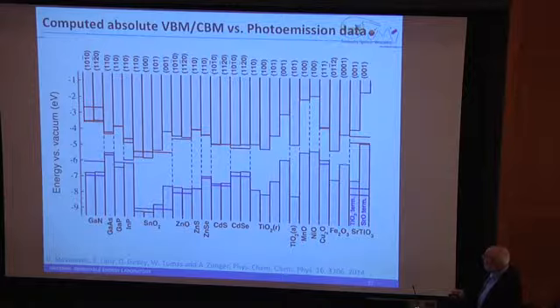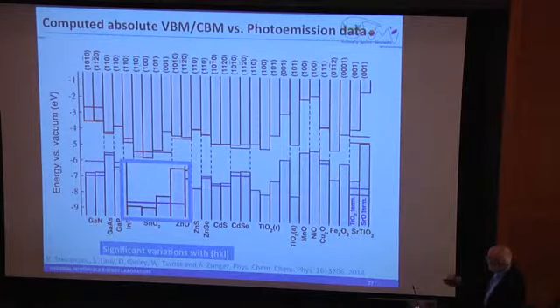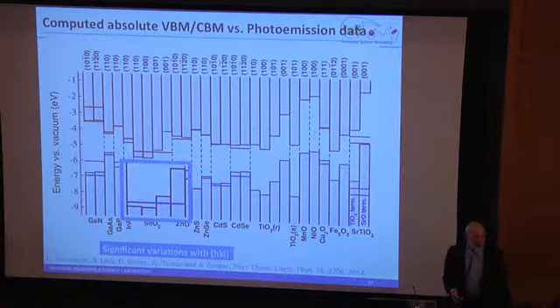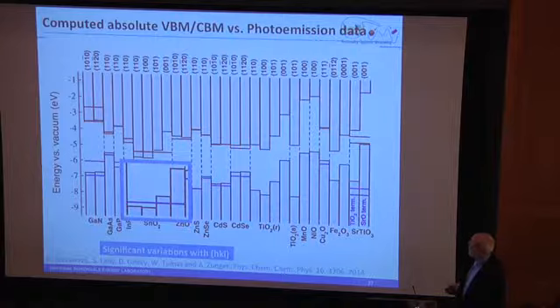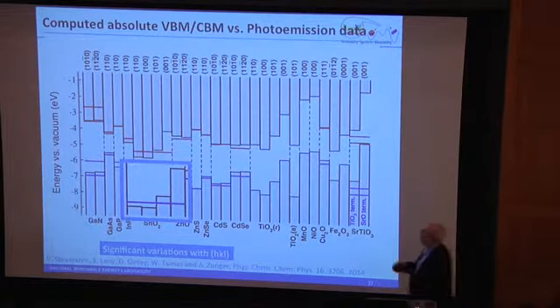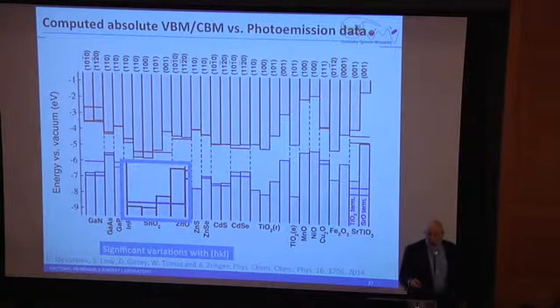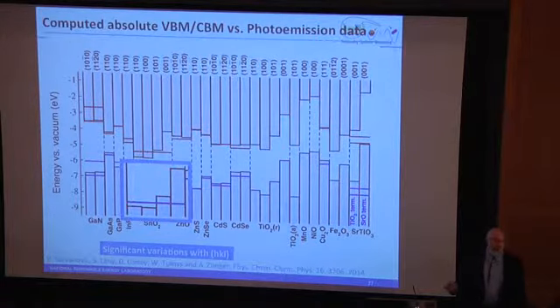You notice that in some cases, like tin oxide, different surface orientations have vastly different photoemission energies. And so this tells you that if you're right about which one's the important one, that's fine, but if you're not, then you're going to be off substantially. And so we blow this up a little bit, and you can see just how big this is. That's almost 1.5 volt change between the low energy surface and some of the other surface energies. And what this says is that if we're ever going to do this really well, we're going to have to be able to go back and calculate all the surface energies that you might get in a polycrystalline assemblage. And so we're actually doing that. I'll show you that for one particular system in just a couple minutes.